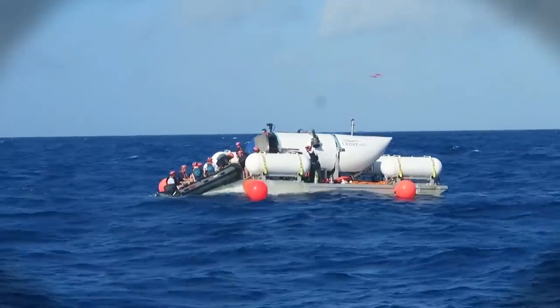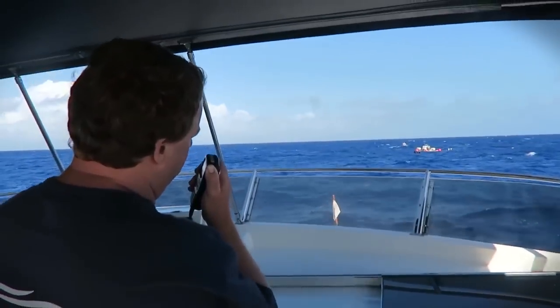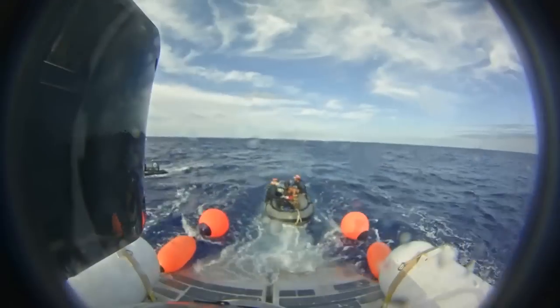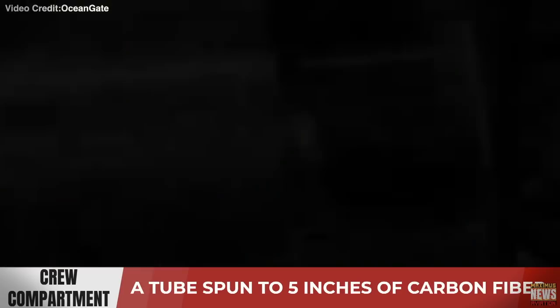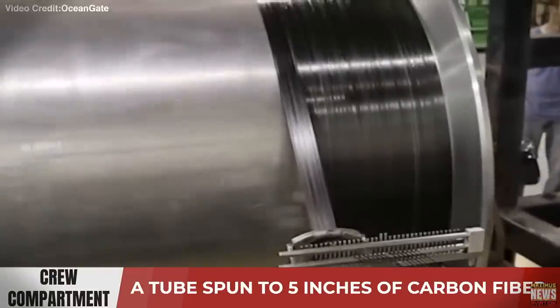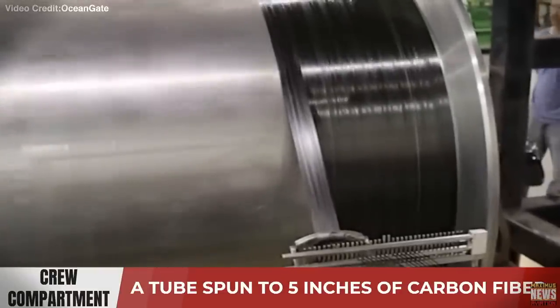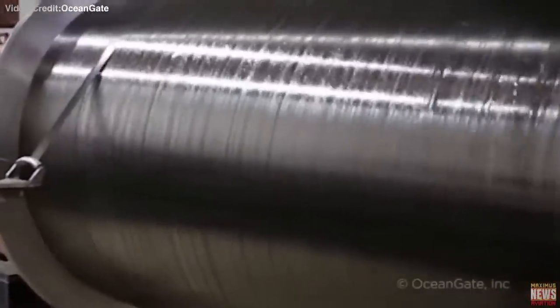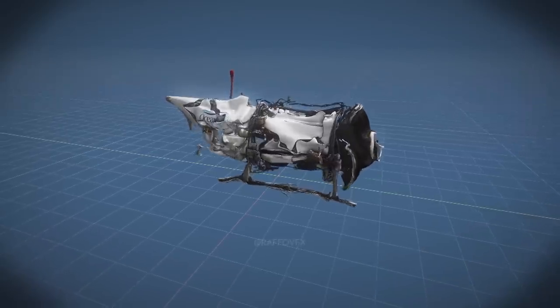However, the Titan's voyage to explore the Titanic was marred by a tragic event. While descending into the Titanic wreck, communication with the submersible was abruptly lost. It was later determined that the Titan experienced a catastrophic implosion, an intense collapse inward, attributed to the compromised integrity of the carbon fiber hull. This devastating implosion tragically resulted in the loss of all 5 passengers aboard the submersible.